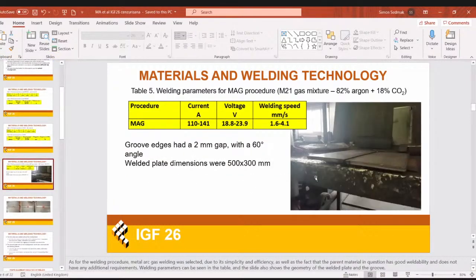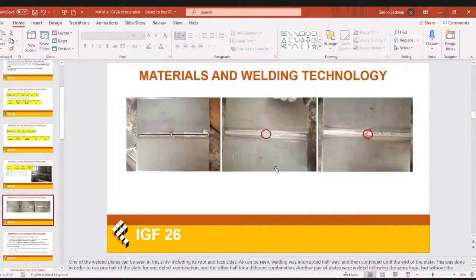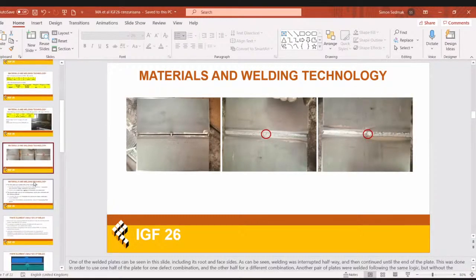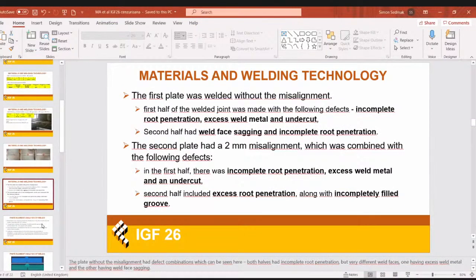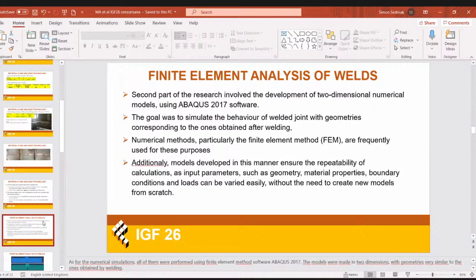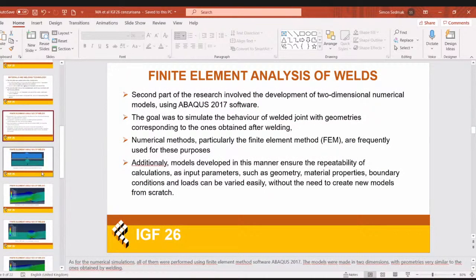So here you can see how we prepared some of the welds. Here there is the actual 2 millimeter misalignment, which we suspected would have a very adverse impact on the structural integrity. And here you can also see how they were welded. One half of the plate would have one combination of defects, and the other half would have a different combination, and then specimens would be later cut and tested. So here you can see all of the combinations of defects, which I had already mentioned. Won't go into detail too much about that.